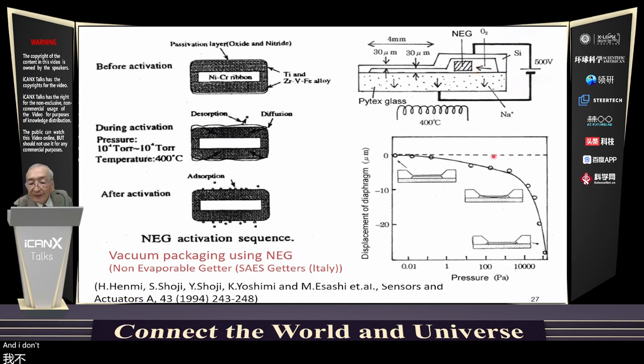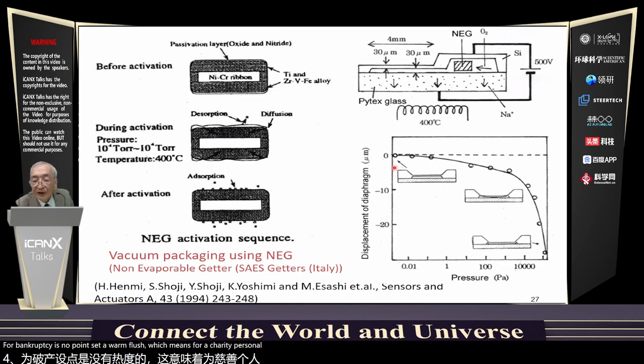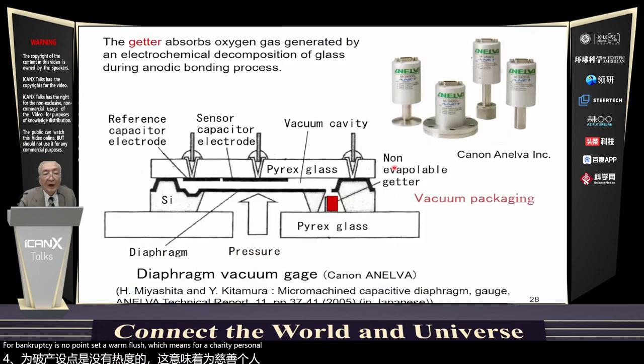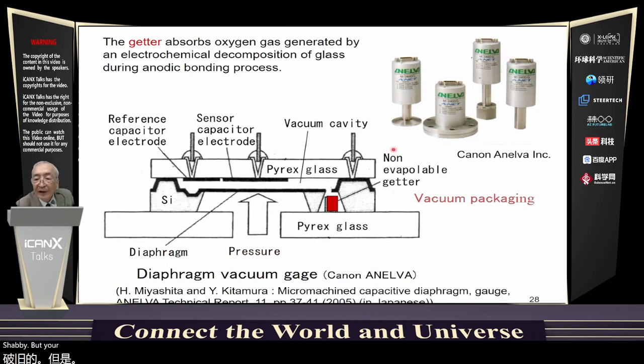The lower graph shows measured displacement of the diaphragm versus outer pressure. The diaphragm is deflected even at 0.01 Pascal, which means the cavity pressure is kept at less than 0.01 Pascal. This technology to make the vacuum cavity was applied to a silicon diaphragm vacuum gauge, and this was commercialized in Canon Anelva. Small pressure difference can be detected capacitively using a thin silicon diaphragm.